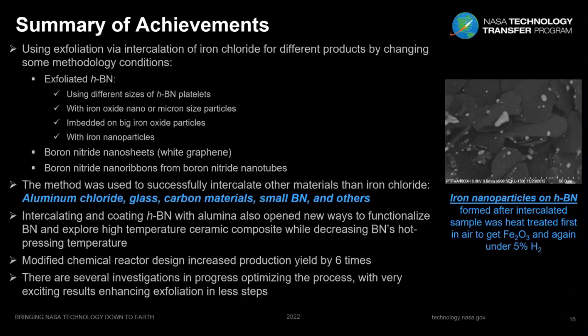A summary of the things that we have accomplished with this method: we can exfoliate using the intercalation of iron chloride, for different products by changing some methodology conditions. With exfoliated hBN, we can have different sizes of hBN platelets. We can intercalate with iron oxide, nano or micro size particles, embedding hexagonal boron nitride in big iron oxide particles. And we can also create metal iron nanoparticles.